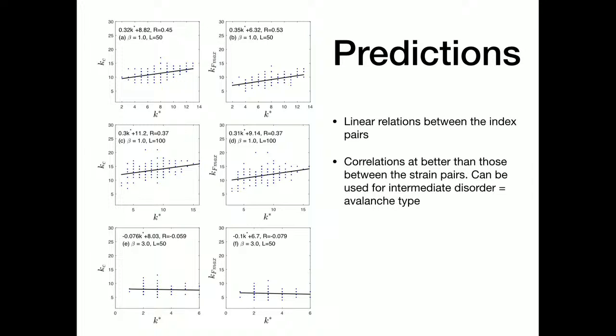So if we look at the record index K star where the maximum strain interval occurs, and then look at Kc and K star and Kf max, this is the maximum peak or the peak load, we see that now the Pearson coefficient is somewhat better, but as you increase the system size, it tends to deteriorate somewhat, but it's definitely a better indicator than the strain pairs, and can be utilized, and it is best for intermediate disorder when you have avalanche type. So this is beta equal to 1, where you see